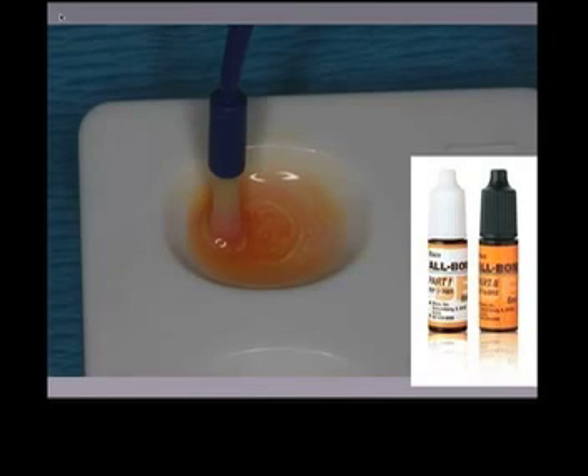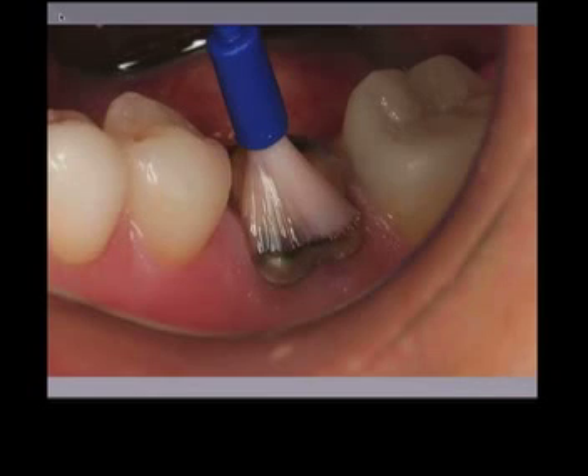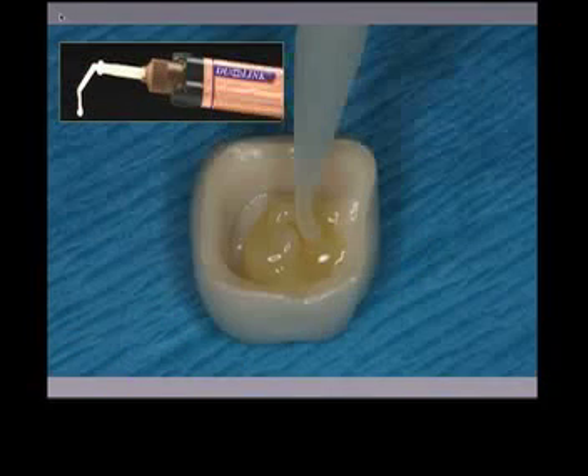Two coats of All-Bond SE in an agitating motion to fully incorporate it within the smear layer, fully air dry beginning from a distance and then gradually moving toward the tooth for 20 seconds. Dispense the Duo-Link within the crown and spread to the walls, and communicate with your lab in understanding the amount of gap between the tooth and the indirect substrate.